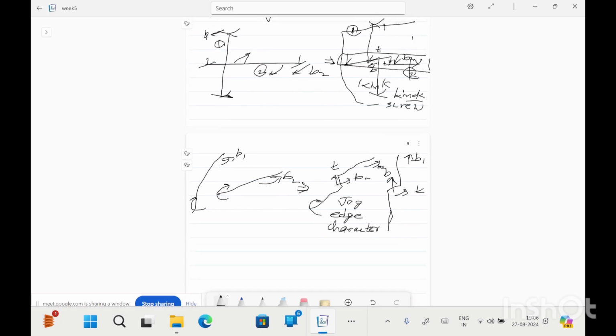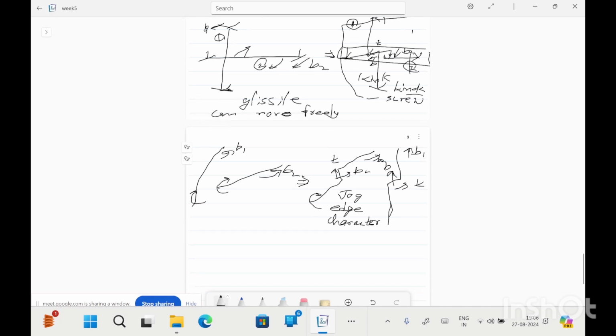So in the edge dislocation intersection case, the steps are in the original slip plane and they can glide freely as they lie in the slip planes of the original dislocation. Means the steps formed in the two edge dislocation interaction are glissile in nature. Glissile means can be easily moved, can move freely. While for the screw dislocation interaction, a jog of edge character forms which is sessile in nature, means cannot move.